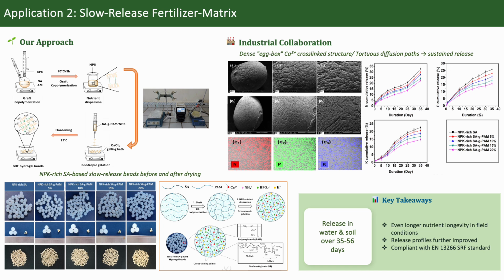The release behavior was evaluated in both water and soil. The results showed a sustained release over 35 to 56 days with profiles compliant with the European norm standard for slow release fertilizers. The release mechanism follows a non-Fickian diffusion behavior, which means that nutrient release is governed by both diffusion and relaxation of the polymer network.